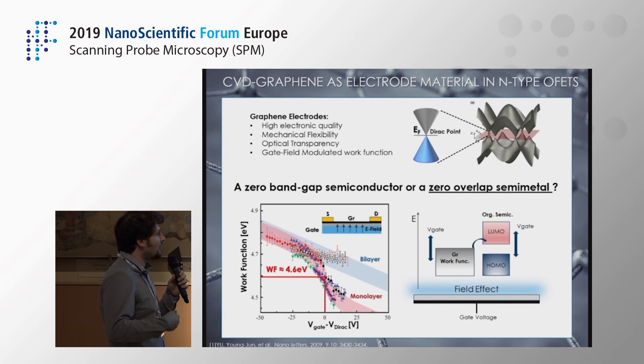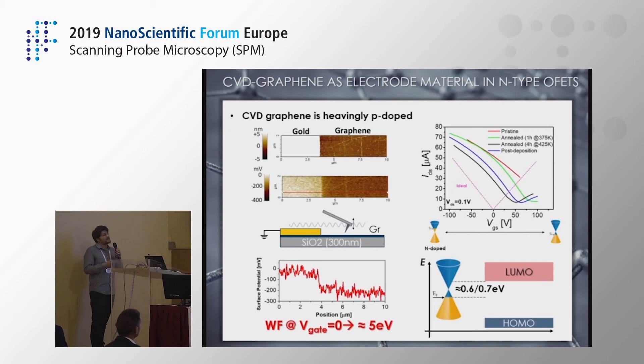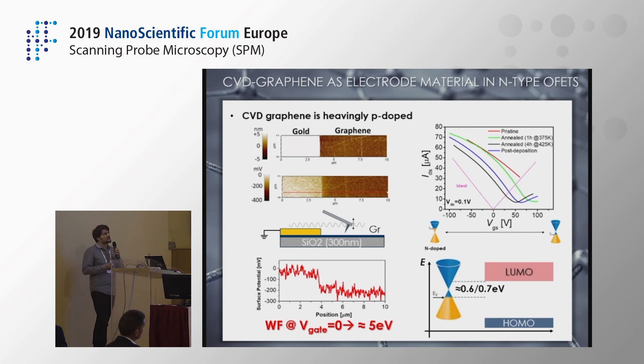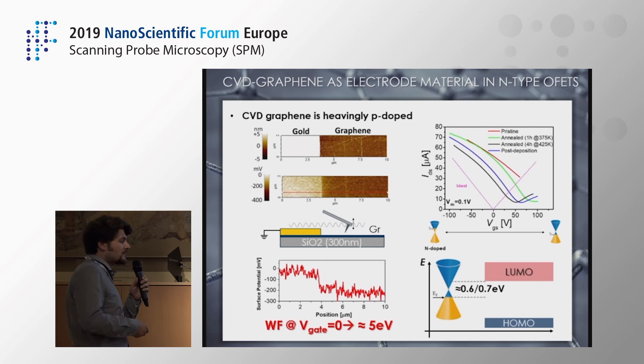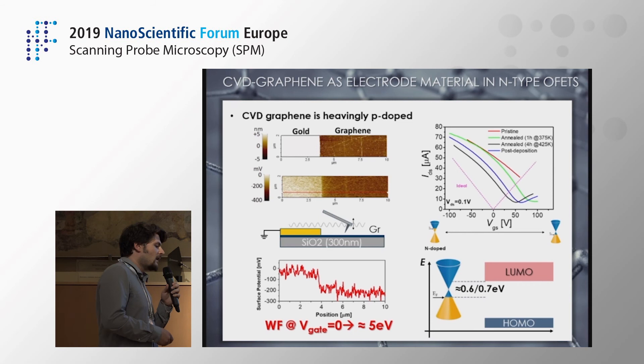We first tested our graphene electrodes in a field-effect transistor configuration where graphene is the semiconductor. CVD large-area graphene is far from ideal — it is typically highly p-doped. This is confirmed by Kelvin probe analysis: mapping the work function over a broad area of our electrodes, we estimated a work function of about 5 eV at zero gate voltage, so something more similar to gold than to intrinsic graphene, at least for CVD graphene.